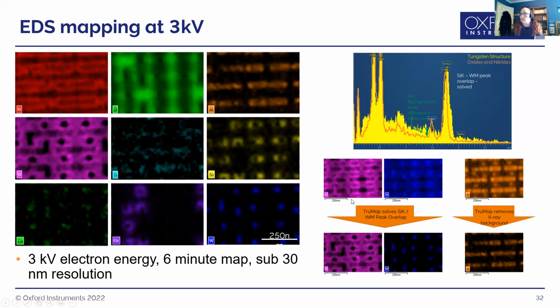So here we've got the difference between the silicon and the tungsten maps. And if you remove that peak overlap and you resolve it, it's essentially a deconvolution. You can see the resultant data down here. And you can also see that in the aluminium there, how we're improving the maps and making sure that we're only displaying signals that we're certain are from the right peaks.